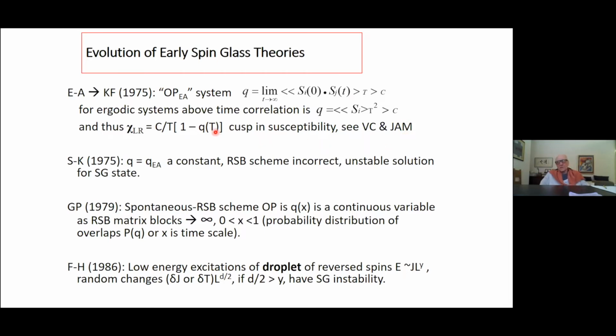Edwards and Anderson then, using mean field, using linear response, calculated the susceptibility. It's Curie-Weiss, and here in the numerator, there is the onset of this Q of T. At a certain temperature, Edwards and Anderson were able to show that there appears a Q of T rather sharply, and this is the famous cusp in susceptibility that we propagated before. So we go back now to the end of 1975. We have Sherrington and Kirkpatrick. Sherrington and Kirkpatrick used the Edwards and Anderson order parameter. It's a constant. This is a single order parameter, and they did a real detailed calculation of all the properties, all sorts of transformations using this trick, the replica trick.